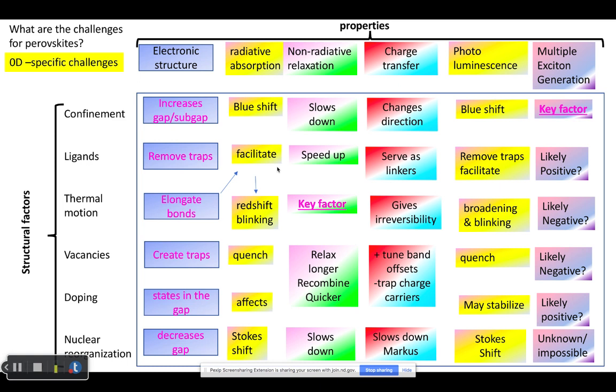What is expected before you report results? So confinement, which means your piece of semiconductor is smaller than bulk, may increase gaps and subgaps, induce blue shift in absorption, slow down relaxation, change direction of charge transfer because it changes alignment, as we discussed for the London project, makes also blue shift for photoluminescence, and confinement is a key factor for multiple exciton generation. Without confinement, it is a very inefficient process.